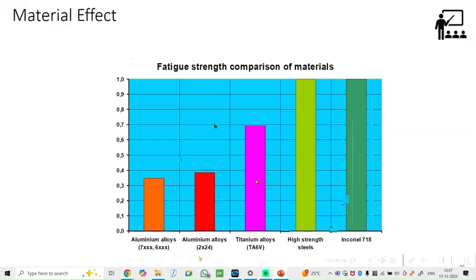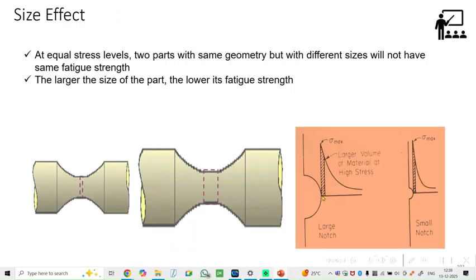Then surface finish, you have already seen rough and polished. Fatigue is a surface phenomenon, depending on the surface condition. If it is rough, the crack will initiate early, so life with polish will be better. That's why, when they generate an S-N curve, they use mirror polish to be consistent. Size effect we have also seen. It affects not only the endurance limit but also fatigue life, because the larger the part, the lower its fatigue strength. When subject to cyclic load, more volume comes under the maximum load, so that affects life.